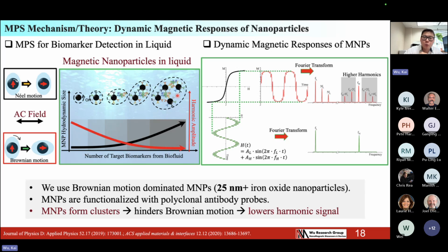So what we observe is a very simple structure where we apply the two AC magnetic fields. And we also have the magnetization curve of the superparamagnetic nanoparticles. The time domain response of the particles' magnetization, or magnetic moment, will be modulated by the AC magnetic field. So this modulation process will generate higher harmonics that do not belong to the field we apply. They belong to the particles' dynamics process. So we compare the higher harmonics produced by nanoparticles to the field, using the FFT, the frequency domain of the field we apply. These harmonics are the signal we use to calibrate or quantify the dynamics of nanoparticles in the case of the amount of analyte in the solution.